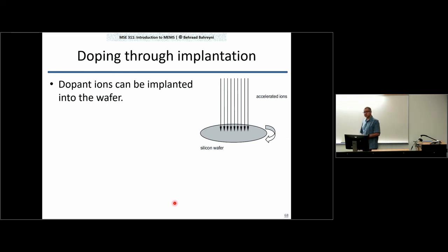With implantation, I have more control. So in this technique, the third one that we mentioned, you ionize dopant atoms and you shoot them towards the substrate. You can do that at different densities of the ions, and you can do that at different energies of the ions. And with those two, you can get whatever doping level you want at whatever depth you want, in theory, right? Now, because you're shooting these dopants into the substrate, it's an atom nonetheless. It's not really going to penetrate that deep.